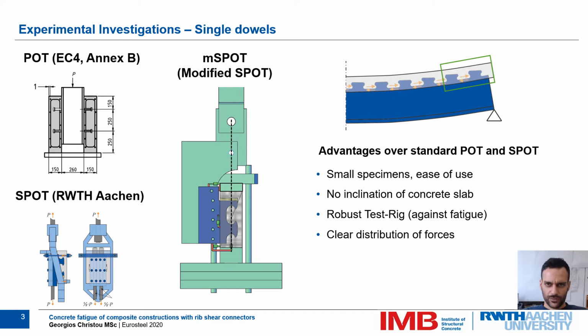For the investigations of local effects, we chose a modified single push-out test. While in typical push-out tests, as suggested in Eurocode 4, shown in the upper left corner of the slide, the forces are distributed unevenly in the dowels. In single push-out tests, the force is introduced in just one dowel, thus providing a precise characteristic dowel curve. The previously used single push-out test rigs, as shown in the lower left section of the slide, had the disadvantage of an eccentricity due to the shifted lines of action. The latter led to fatigue of the test rig and premature termination of the test.